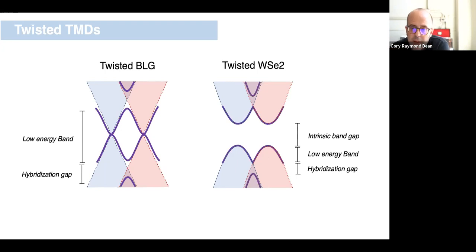That hybridization gap basically cuts off, in this case, the top of the valence band or the bottom of the conduction band. And again, I end up with an isolated low energy band in the system. In this case, however, the position at which this hybridization gap emerges is a function of angle, and the size of the gap is related to the degree to which the bands hybridize. But now I've got a hard stop in this band. I'm bounded by the intrinsic band edge.